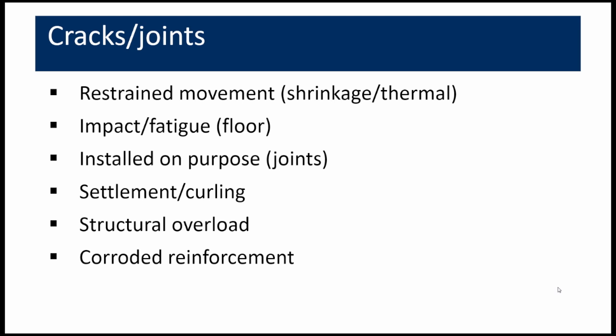So typical conditions, and as I mentioned, we'll start off with cracks. Well, we're familiar with cracks. Cracks are commonly caused by these phenomena shown here. Restrained movement is a common one, where we have shrinkage or thermal movements that are restrained, causing stresses that are associated with cracks. We have impact and fatigue, which most people think of in the context of steel, yet concrete does experience this phenomenon as well. We have joints, which are installed on purpose, which are essentially cracks, except for controlling the location where they occur. We have settlement and curling that can cause cracking.